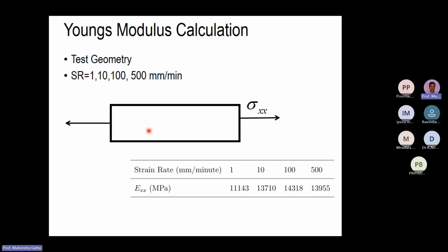And for material property calculation, we tested this specimen with no notch, and we got the Young's modulus value for different loading rates. So for 1 millimeter loading rate, we got 11.1 gigapascal. For 10, it is 13.7. 100, 14.32, and 500, it is 13.9.